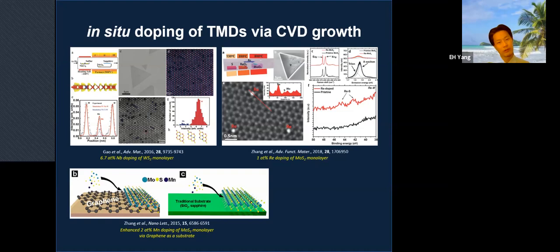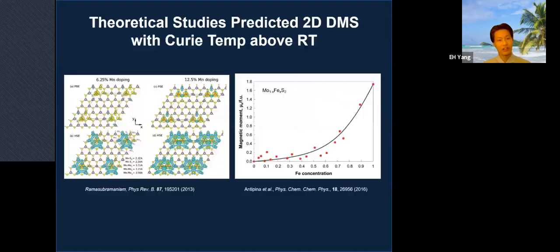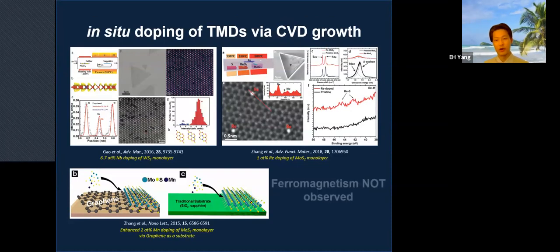In situ doping means that you dope as you grow. And one paper on the bottom actually is about the manganese doping. Interestingly, this manganese doping was supposed to provide room temperature operation, but actually none of these papers show any ferromagnetism at any temperature. No ferromagnetism, okay? So it's easier said than done.